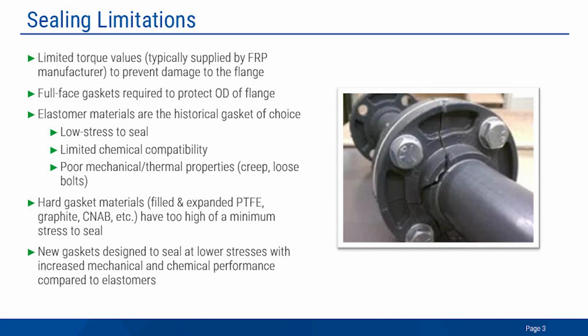The issue with elastomer gaskets is mostly on the mechanical side. So anybody who uses rubber gaskets knows that you can tighten a rubber gasket up. It will pass that initial leak check just about every time because it is a great sealing material, but give it a day, a week, sometimes even an hour, it will relax and lose at least 50% of its bolt load shortly after tightening it up. So while you can get a reliable seal on startup, typically they don't have a very long service life because eventually you will lose that bolt load, you'll lose torque, and you'll either have loose bolts or you will just have a leaking flange connection.